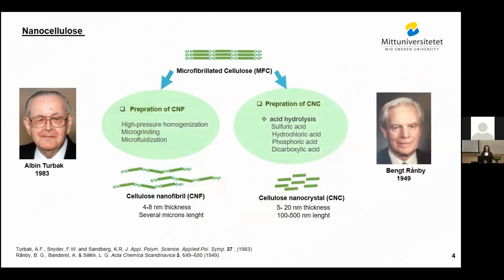In a microfibrillated cellulose, we have both amorphous part and crystalline part, and dependent on the treatment of the cellulose fiber, we can manufacture two kinds of cellulose, CNF and CNC. With the fibrillation of cellulosic fiber, we can produce CNF under high mechanical shearing, and with the acid hydrolysis, we can break down the amorphous part and release the crystalline part, so that we will have a crystalline nanocellulose.